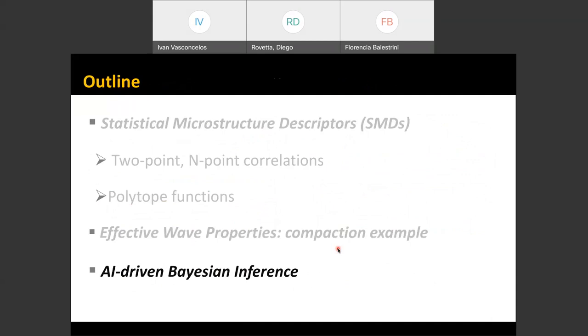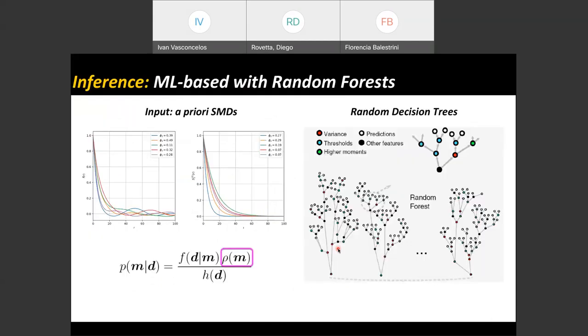And this leads us to the last part of our talk, and that's where we talk about inference. So how do we treat this problem? Well, the relationship between the microstructure descriptors, so curves like the ones that you see in these plots here, so you can see the Fs, you can see some S2s, you can pick different types of these curves, and the properties of the microstructure, namely volume fraction and contrast, the relationship between these curves, volume fraction, contrast, and effective properties is actually highly nonlinear. So if you wanted to do an inversion in a Bayesian sense, your best choice would be to choose something like a Markov chain Monte Carlo sampler. But of course, you'd have to repeat that every time you get the data.